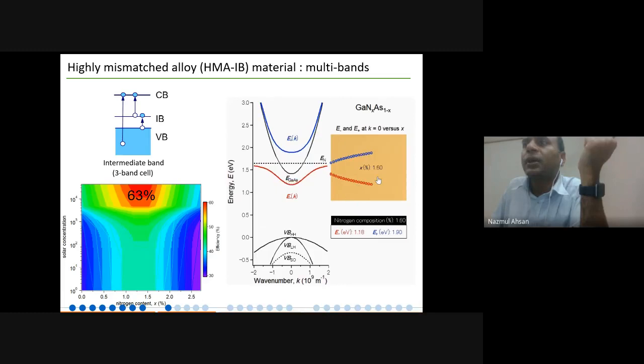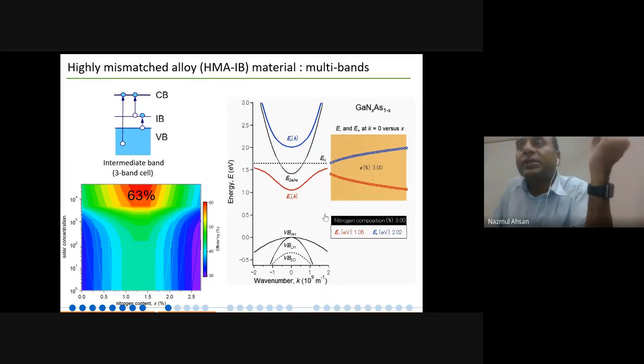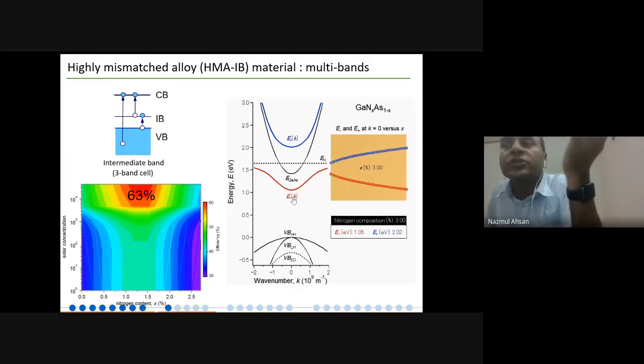And there are the numbers of the band gap. For the red one, for 2% of nitrogen, the lower band gap. Okay, let me start from the very beginning. At 0%, my original band gap was 1.4 electron volt. But for 3%, the red band gap is, let's say, 1.06 electron volt, and the largest band gap is 2.02 electron volt, and this band gap should be 2.02 minus 1.06. Now if you bring in sunlight, the short wavelength photons will be absorbed from here to there, and long wavelength photons should be absorbed either from here to there or from here to there. So this is very close to a 3-junction solar cell.